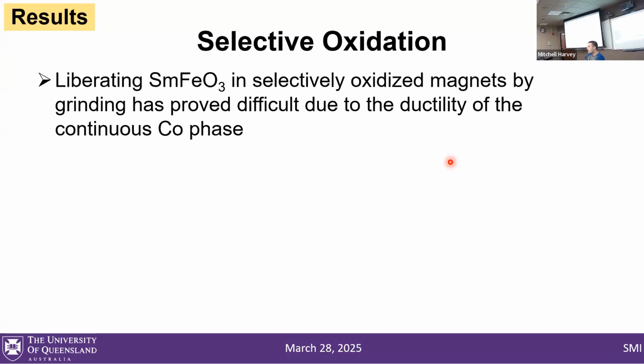Liberating the samarium ferrite in the selectively oxidized magnets has proved quite difficult due to the ductility of that cobalt phase. Those oxide particles are very small, and the cobalt is the continuous phase—the cobalt metal completely encapsulates all the oxide particles. Cobalt is a metal, metals are ductile, and we knew this going into it, but we hoped that if we ground the metals enough, if we cold worked them enough, they would become brittle and we'd be able to liberate the two phases. But that's just not been the case.